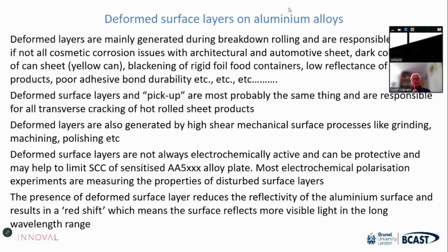reflectance. And it's really through control of these layers, once we discovered they were there and we could investigate them in great detail, that we could understand how to properly clean surfaces and how to properly pre-treat surfaces and how to properly coat surfaces, such that we could get a much better surface experience. So this work has been absolutely critical in really determining how things work in service and in expanding markets for aluminium alloys in automotive, packaging, and architectural applications. So really critical stuff.